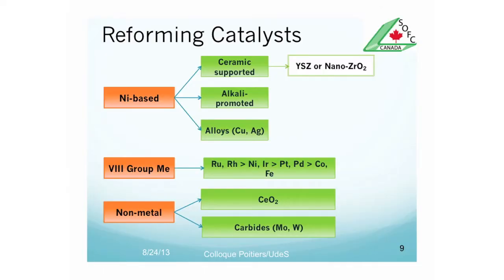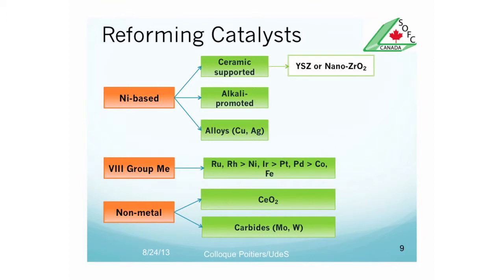we have three types of catalysts: nickel-based, metals of the 8th group of the periodic table of elements, and non-metallic catalysts. The nickel-based are essentially ceramic supported, alkali promoted, or alloys with copper and silver. I will not go into details for all this, but what I can say is that the ceramic supported are the ones which are commercialized, mainly using alumina, but more and more it is known that yttria stabilized zirconia or nano zirconia is one support which is of very, very high importance for reasons I will explain later.